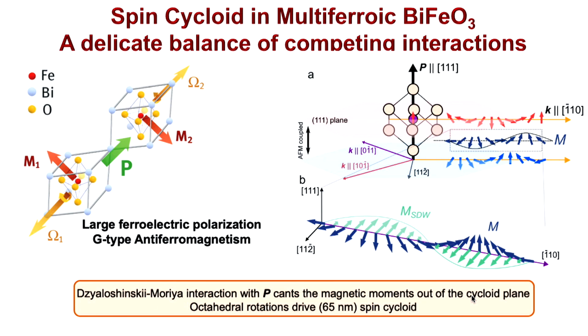Now, there are two things on top of this which make it very interesting. The first thing is, because of this Dzyaloshinskii-Moriya interaction, there's a small canting of these antiferromagnetic planes. It's a very small amount, about 5 emu per cc. And that canting is very important, it turns out, for many different things. If you now look at this schematically, that's the polarization direction. That spin, the canted moment, is not uniform in the bulk. In thin films, it can change, but in the bulk, it's not uniform. But it also couples to the spontaneous polarization, and therefore, it starts to spiral around. And we call it a spin cycloid.